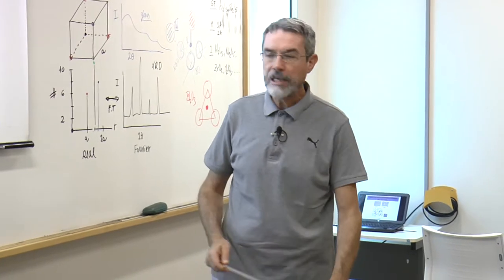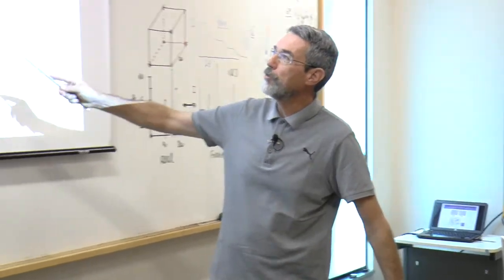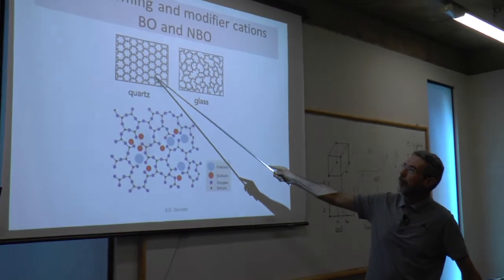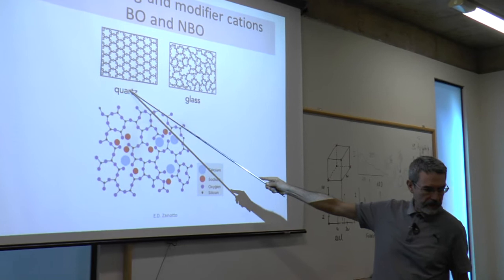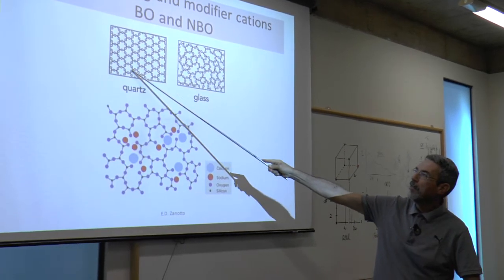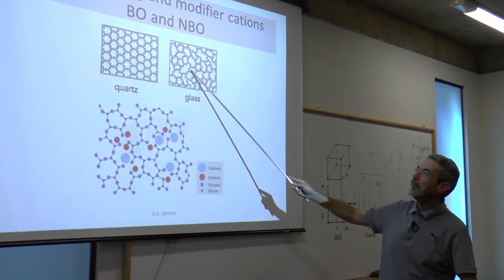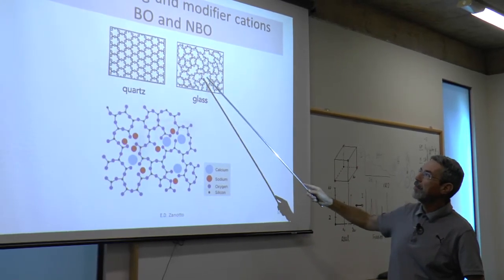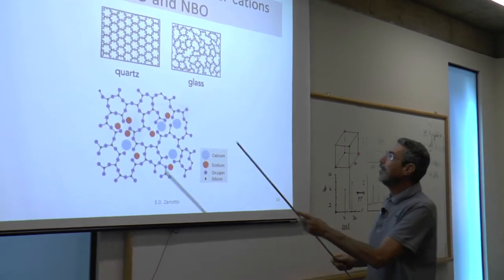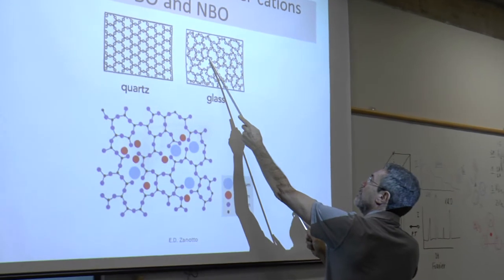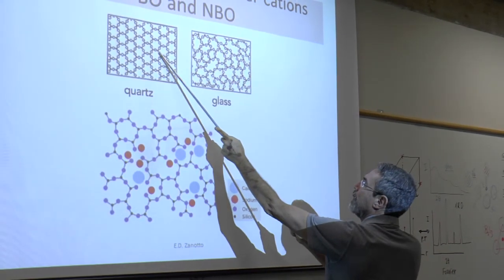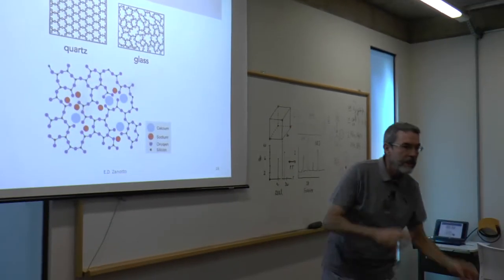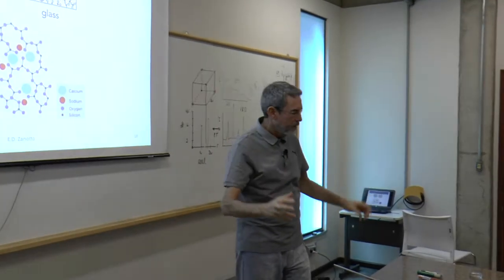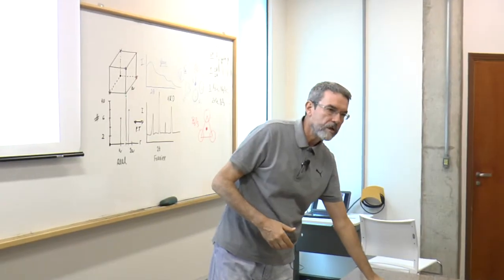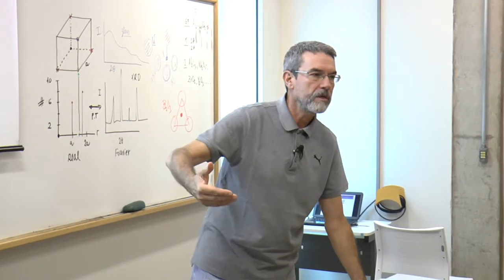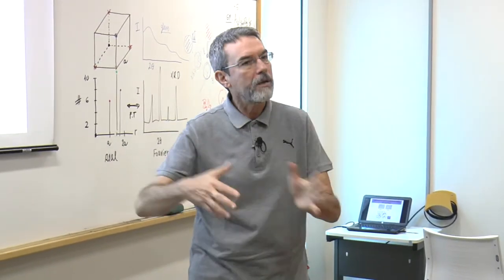Also, I have mentioned this but did not show a picture. This is a picture of the 6-membered rings in quartz, a crystalline phase of silica, and here the glass with 4, 5, 6-membered rings and more. The tetrahedra are exactly the same. You take this tetrahedron here, it's exactly the same as any of the tetrahedra here. Just the links between them are different. So glasses have short range order, but lack long range order.